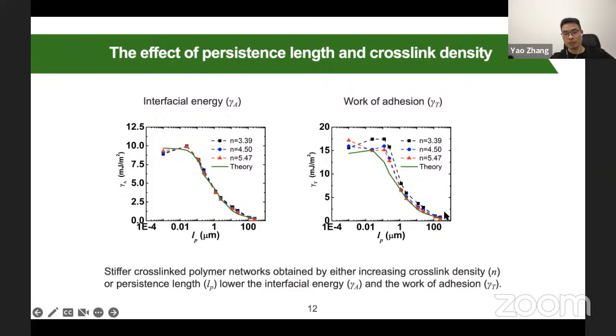So it means that if your fiber persistence length decreases, your network just becomes denser. And the work of adhesion will also reach a max value when the persistence length reaches around 100 nanometer. So what does it mean? It means that if the fiber has a smaller persistence length, the fiber is very flexible and it will form a network with a small pore size and larger mass density, so it will be easier to attach to the surface. It means that you have larger interfacial energy because there's more fiber attached to the surface, and you also get a larger work of adhesion.